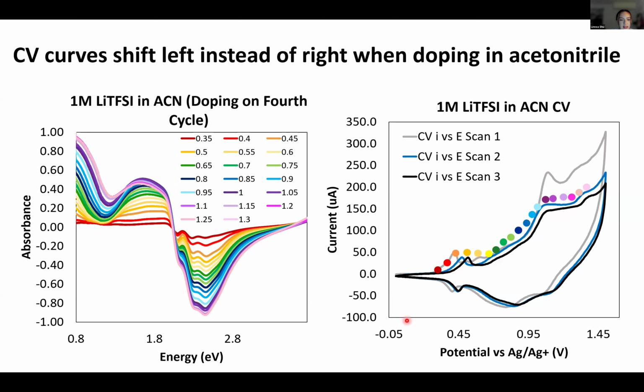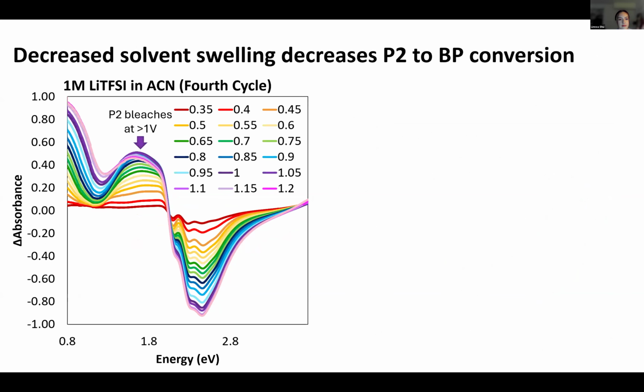Additionally, I noticed when I did this that the P2 peak does not bleach as much as it did when doping with TFSI and propylene carbonate. So this led us to believe that swelling is having some effect on the conversion of polarons to bipolarons at high potentials. So in order to investigate this, this first one was done on the fourth cycle.